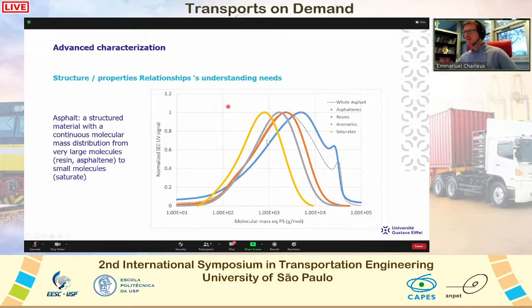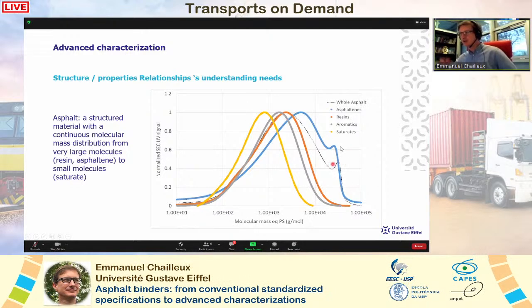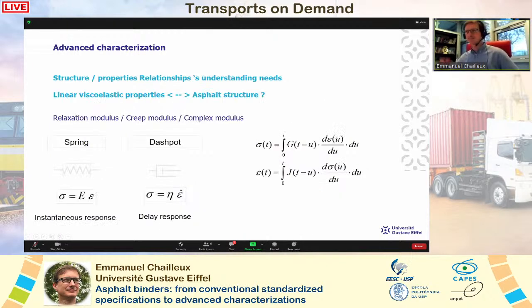So it seems that we have a continuity in the molecular distribution from very large molecules here to very small molecules here, where the saturates are. So it's very important to understand that we have a very complex structure, but also a continuous molecular mass distribution of the asphalt. So the question which arises now is: is there a link between mechanical properties and asphalt structure, or more precisely, is there any relationship between linear viscoelastic properties and asphalt structure?